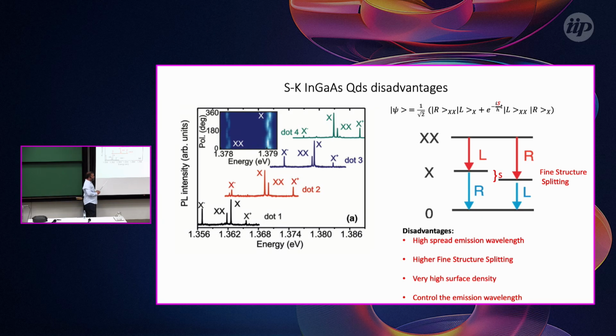And also, one of the biggest problems is the high fine structure splitting. Basically, because of the strain and piezoelectric effects, in general, this neutral exciton energy level will suffer a splitting. And this splitting, sometimes for these indium arsenide quantum dots, is so big that you can kill the entanglement of the two emitted photons. And another disadvantage is that, in general, it's very hard to control the surface density of these quantum dots. And generally, you have to find a way to isolate a single photon source, a single quantum dot on the sample, to measure them. And to control the emission wavelength.